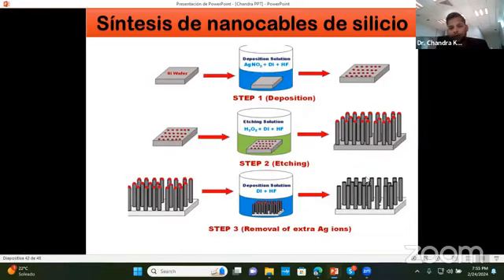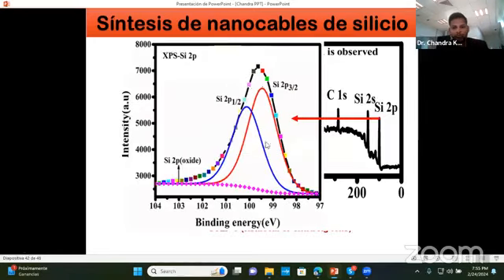Okay. Second, how can we claim to remove the oxide, because if we take silicon, then a SiO2 layer is always present over silicon. How can we claim to eliminate the oxide layer using HF in the final sample? So here, see, if we use the silicon 2P peak in CASA XPS or any such XPS software, you see this is the 2P 1/2 or 2P 3/2 peak. If you see polysilicon or normal silicon, you will get one peak around 103.2. That peak is for SiO2, silicon dioxide.